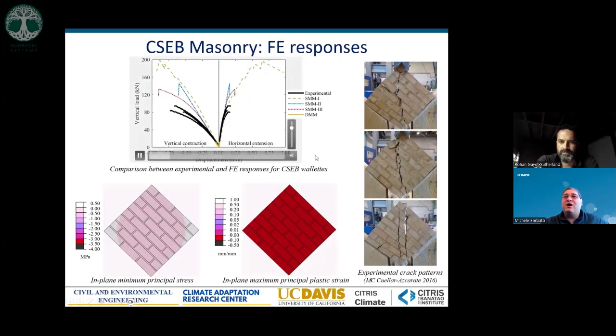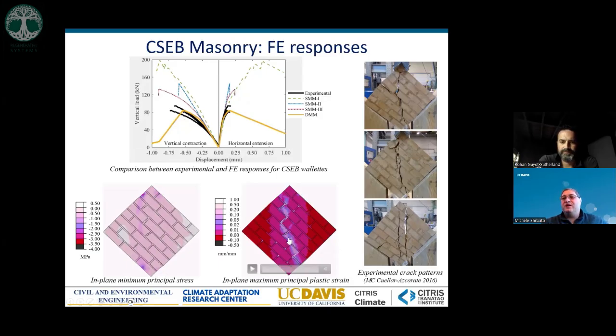So here is when our new model actually starts really doing well. You can see this yellowish line is our new model, which is pretty good in capturing not only the peak strength of the wallet, but also, in this lighter color here, where the formation of cracks is happening. And so our model is able to capture the cracking going through the bricks, which is fundamentally physically impossible to capture with the simplified micromodels. And that is the reason that the simplified micromodels are not able to capture the real strength of these walls.